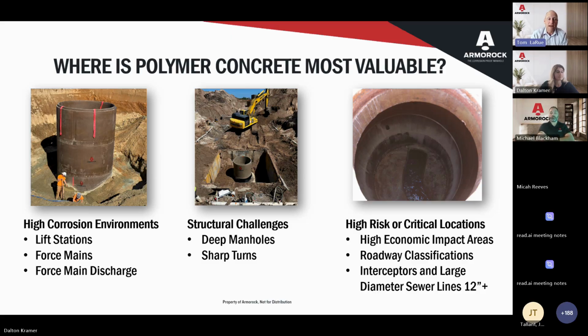Next area is structural challenges. Deep manholes, sharp turns, those become expensive to repair and replace. Excellent application of polymer. And then finally, high risk and critical locations, high economic impact areas. We've seen major distribution centers where it would be very costly if they're shutting down the distribution area, use polymer concrete. Roadway classification, if it's a busy street, busy intersection, very expensive, very detrimental to the community to have to shut down those areas for repairs and replacements. Jurisdictions are requiring polymer used in those locations. Finally, interceptors, large sewer lines greater than 12 inches. That's a prime place to use polymer because those are areas with higher levels of H2S and more expensive to repair and replace, things that you want to do one time, be done with it, and have the infrastructure last for generations.